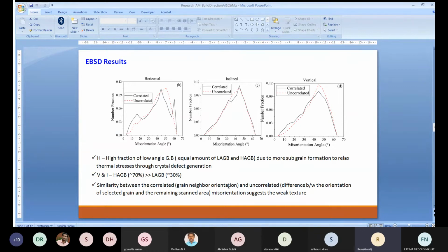So what we understood, interestingly, is that the horizontal direction has a high fraction of low angle grain boundaries, about 50%, whereas in inclined and vertical we have about 30% low angle grain boundaries. Low angle grain boundaries are very beneficial because they ensure more dislocation density, and they also ensure more subgrains inside the grain structure. Inside a single grain, more subgrains will be there. These are the ones which are going to help you improve the ductility of the material.